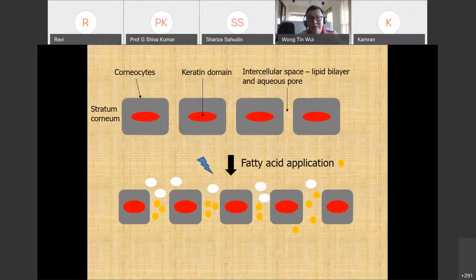Now, to understand a little more about the complication brought about by fatty acid, if you look at this diagram, upon treating the stratum corneum with microwave, we have a larger intercellular route favorable for insulin delivery. However, if fatty acid is applied, it is found to accumulate within the intercellular route, and it forms a hydrophobic shield or hydrophobic barrier. Knowing that insulin is a large molecule drug and it is highly hydrophilic, it will be very difficult for the hydrophilic, large molecular weight insulin to penetrate across the intercellular route due to its hydrophobic nature, right? Although the intercellular route has been enlarged, due to the hydrophobicity, the insulin will not be able to penetrate successfully.